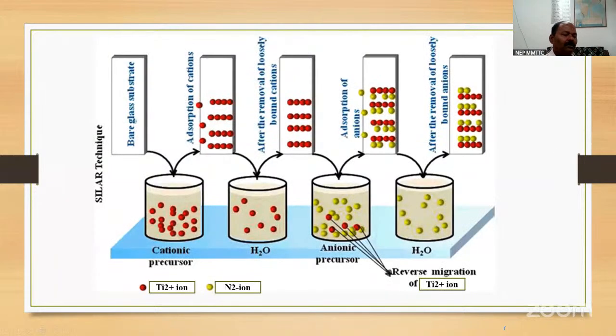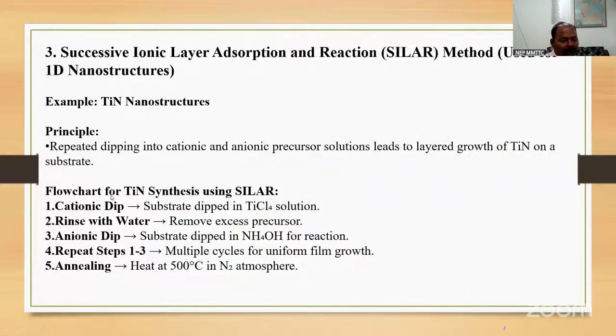Now the SILAR technique, a SILAR method. What is this? Now you see the flow chart for titanium nitride synthesis using SILAR. Cationic dip: the substrate is dipped in titanium tetrachloride solution, rinsed with water to remove excess precursor. Anionic dip: the substrate is dipped in ammonium hydroxide for reaction. Repeat steps 1 to 3 times, multiple cycles for uniform film growth. Now annealing: heat at 500 degrees Celsius in nitrogen atmosphere.